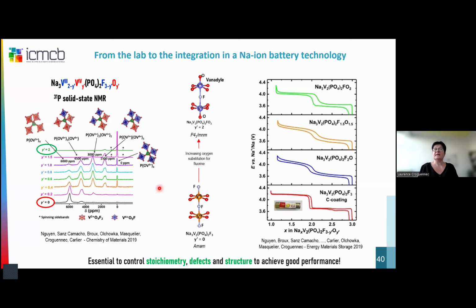And here I wanted also to highlight that in order to really detect these defects and to be sure of the stoichiometry in oxygen and fluorine here, the probe phosphorus solid state NMR is a really good probe. You can see that when you increase the oxygen in these materials, you have more and more NMR signals, in good agreement with the fact that when you do not have oxygen, your phosphorus here is only surrounded by vanadium 3+ octahedra. And the more you have oxygen, you increase the number of vanadium 4+ octahedra around it, and you change the transfer, the electronic transfer from the vanadium to the phosphorus. And so it means this shift from high shift in NMR to diamagnetic shift in NMR.